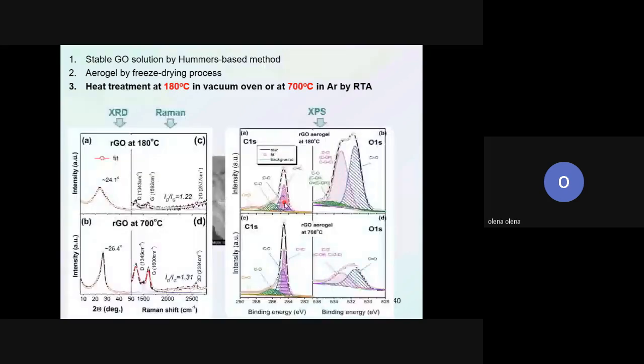And we continue the study by X-ray. You see the position of the peak in the case of reduced graphene oxide annealed at 180 is at a lower position in comparison with reduced graphene oxide at 700. What does it mean? It means that the interlayer distance decreases with increasing temperature. It means there is not so big a space for the electrolyte ions.